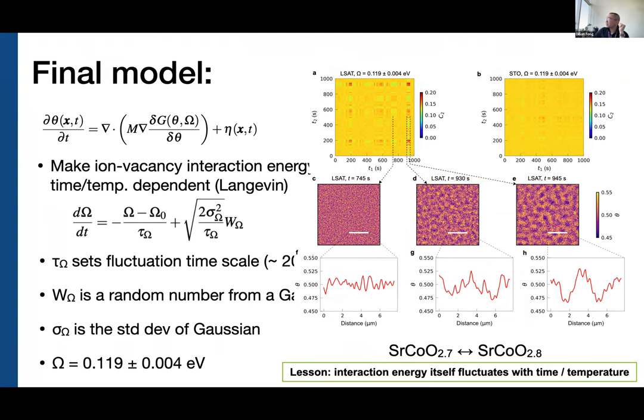At different points in time, at 745 seconds, you might see this for your structure. You can look at the middle horizontal panel, where the horizontal bar is about 8 microns in width. That plot at the bottom shows an 8-micron plot where there's some variation in the oxygen concentration. That small variation in oxygen concentration comes from that noise term.